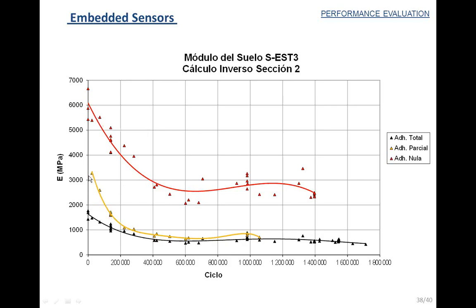In order to do this back calculation, the yellow dots, we were also using instrumentation from the sections, because if you have loss of the modulus of the cement-treated layer, or you have loss of bonding, that would make a very big difference in the asphalt strain at the bottom of the asphalt layer. So we used that data from the sensors in order to do the back calculation, and the yellow point is what we obtained. And we believe that at the beginning the bonding was lower because the modulus of the material was very high, and then at the middle of the test the bonding was better because the modulus of the cement-treated layer was much smaller.